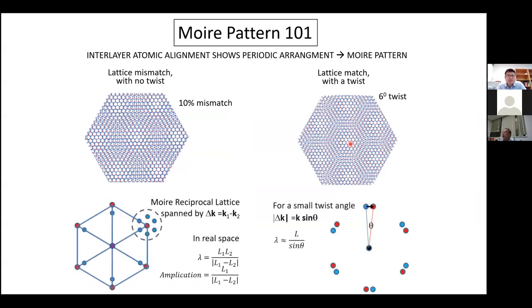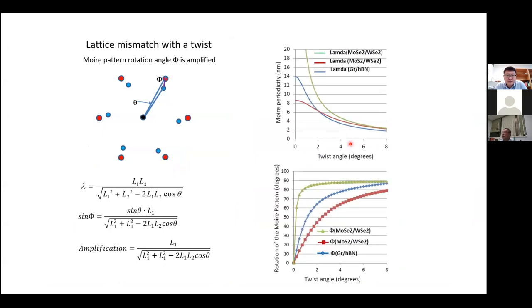All right, I'm going to skip this part because of the time, but I think moiré pattern is such a hot topic, probably most everyone knows about it. The only thing that I want to point out here is, if you take a nearly lattice-matched system and you try to create a moiré pattern, its periodicity is extremely sensitive to the twist angle. But if you choose one with a larger lattice mismatch, then this dependence of moiré periodicity on the twist angle is a lot weaker. And I believe this very sensitive dependence on twist angle is largely responsible for why in the MoS2, WSe2 moiré exciton, there's still controversy behind it.